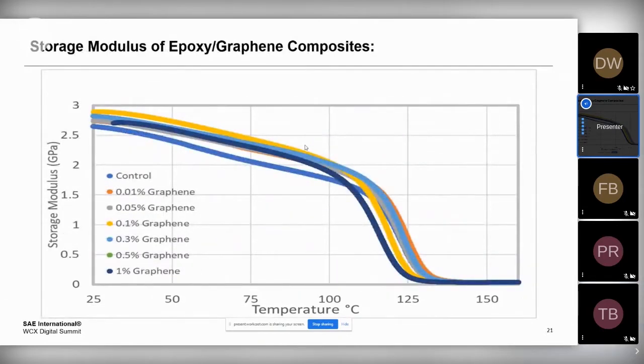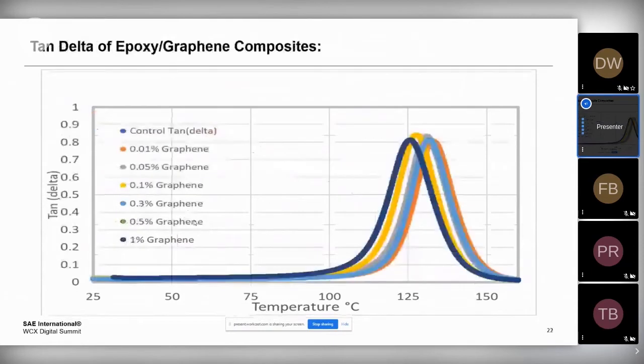We'll look at a similar situation with an epoxy and a graphene application. And with the epoxy graphene application, we can go to, again, about 0.1% graphene, and that's a very, very low loading of graphene that will allow you to achieve a significant gain of about 18% in terms of your modulus. Again, in terms of the crosslink density, we have to be careful too, because graphene, if it's not dispersed properly, can affect your crosslink density when you're trying to do a polymerization by steric interference. But in this case, we're finding that the impact is not significant.